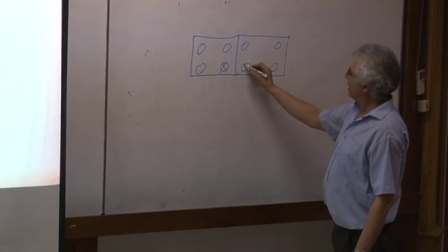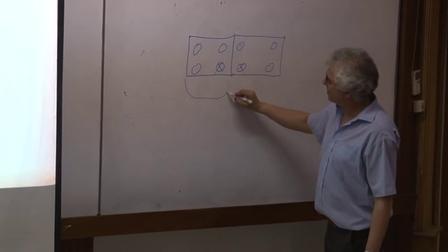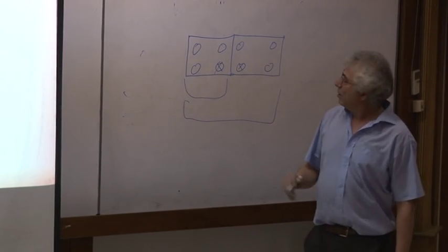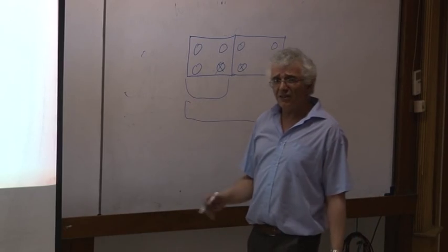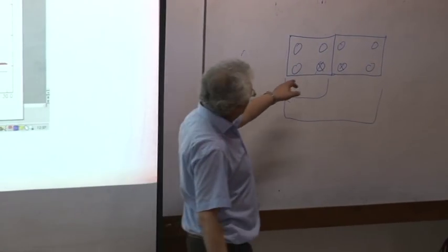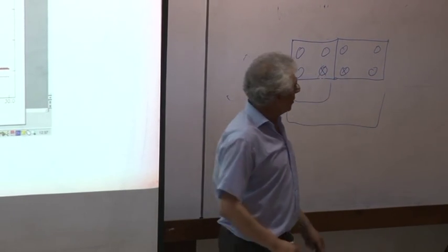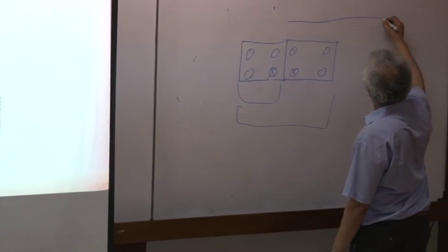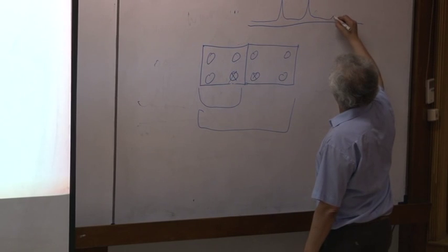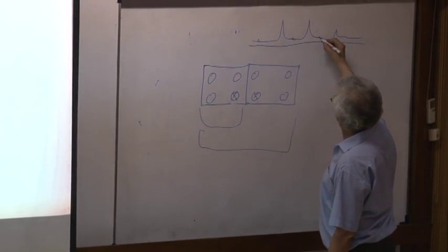Okay, let's say we had two of these together like that. So now your unit cell is not defined by this, but by this. And so all of the rest of the pattern is the same, but you've got ordering associated with the two X atoms here. And what that gives rise to in the pattern, so if you look at a normal diffraction pattern, you'd have peaks associated with the main phase, but then you would get little peaks associated with this ordering.